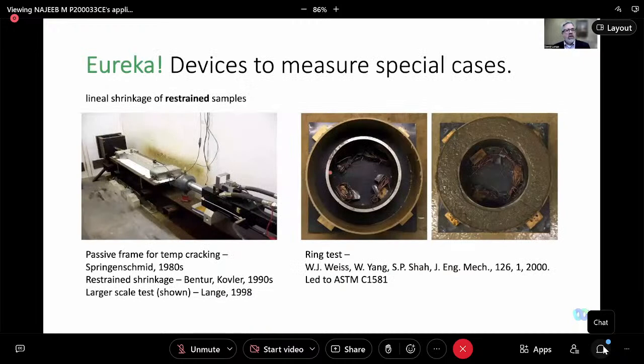Well, we certainly have seen some eureka moments in this field of measuring shrinkage. And I want to cite this very nice test that we built off of Springenschmid's model in the 1980s when he was doing passive frame for temperature cracking. And then Arnon Bentur and Kovler in the 1990s used this kind of configuration for restrained shrinkage. The actual test that I show on the left is from our test at U of I, a larger scale test. And basically what we're doing here is casting the concrete in a test configuration where we can apply a load and measure the shrinkage of the sample simultaneously.